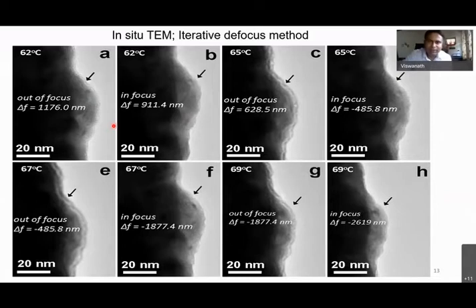I'm just trying to show the bright field image. It is not a great quality image, but what we are looking at here is only the Fresnel contrast. If it is out of focus, we have either over focus or under focus. So we'll clearly have either a dark fringe or a bright fringe based on the focus. So it is initially 62 degrees Celsius, and the sample is, for example, slightly out of focus.